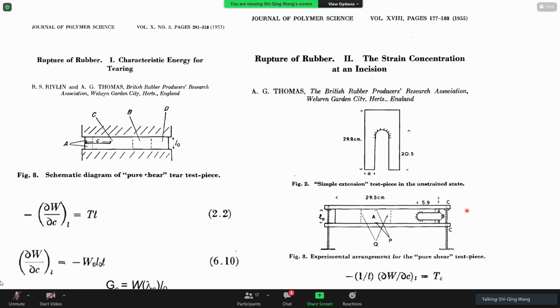He very cleverly thought about using pure shear, as indicated here. The only length scale in the problem is the height of the sample. The other dimensions are much larger. In that limit, he was able to argue, using the approach of so-called energy balance, to compute Gc. He argued that Gc should be given by this last expression here, proportional to the height of the sample, indicating that this is only a matter of energy storage in the entire sample.